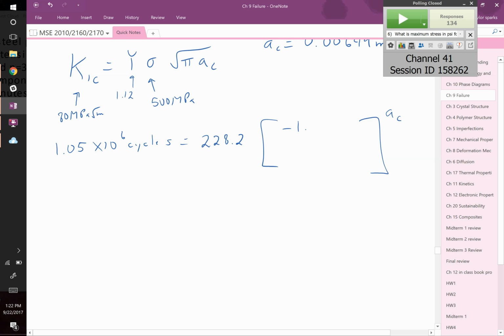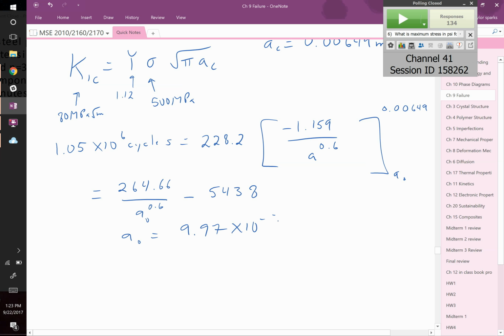If I leave y in the integral, I get 1.159 over a to the 0.6. Right, that's leaving y in, or you could factor y out and have the answer I showed you before. You're evaluating that from a naught, which we do not know, up to ac, which we do know, 0.00649 meters, right? I plug in the next step and I get 264.66 over a naught to the 0.6 minus 5438. And finally, solving for a naught, I come up with 9.97 times 10 to the negative 7 meters.